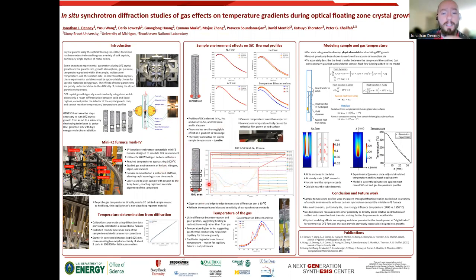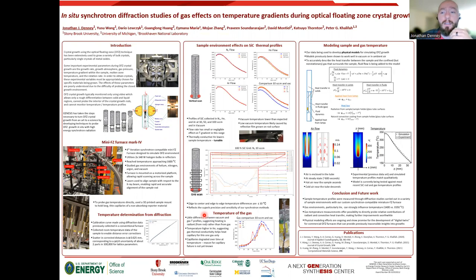In addition, in this set of experiments, we attempted to probe the temperature of the gas via aluminum oxide capillaries in the tube with the rod, but found almost no difference between vacuum and gas except in the case of helium.